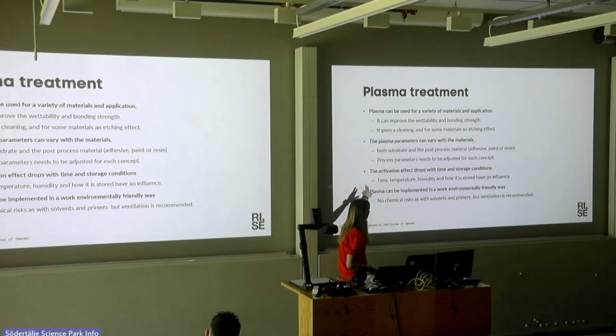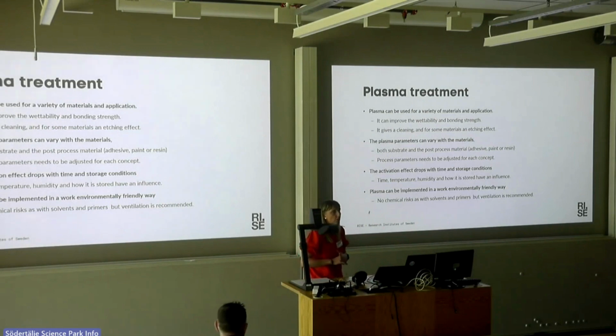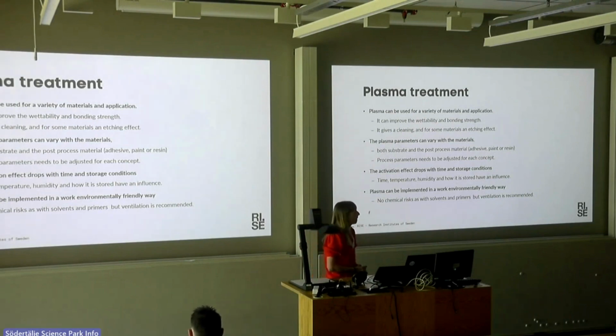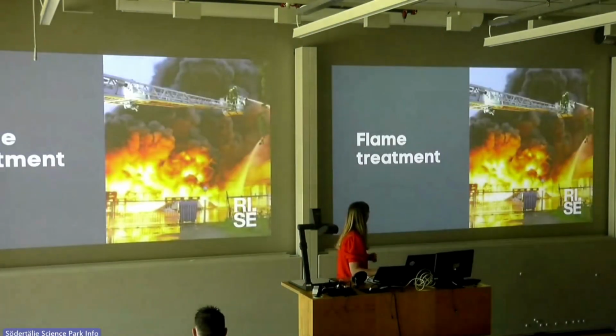And what I didn't mention before is that the activation effect you get with the plasma drops with time and storage conditions. With high temperature and high humidity, the effect drops more quickly than at room temperature and low humidity. How quick is it? Minutes or hours? No, more days. We have done some investigations, measuring after 1 day, 2 days, and 1 week. It's not that it drops completely, and it's also different for different substrate materials.